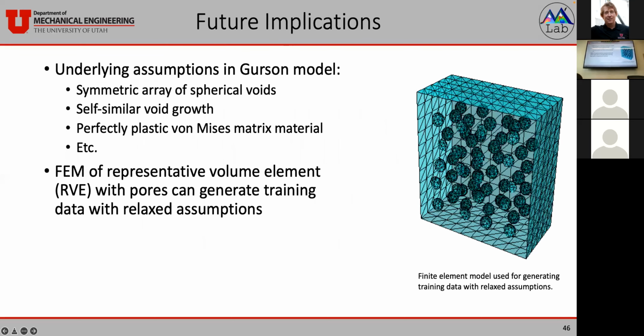As far as future implications go, the assumptions underlying the Gurson model are, again, a symmetric array of spherical voids. They're assumed to remain spherical throughout the loading, which is known to not be physically realistic. And then also the Gurson model assumes a perfectly plastic von Mises matrix material, which again is not very accurate in practice. So what I've shown here is a finite element model with pores, and you can adjust the shape of the pores, adjust the distribution of the pores. And this allows you to generate training data with relaxed assumptions to, in the end, get more accurate models with GPSR than the Gurson model can provide.